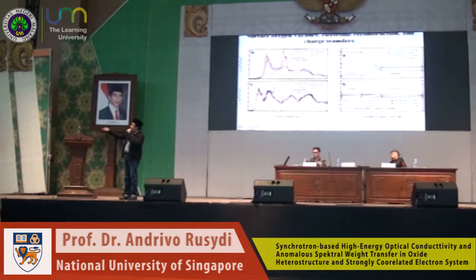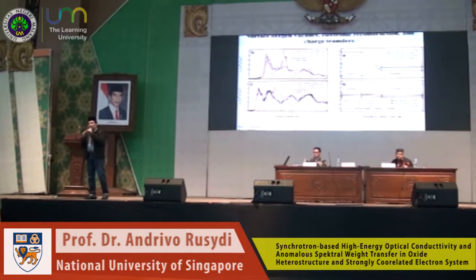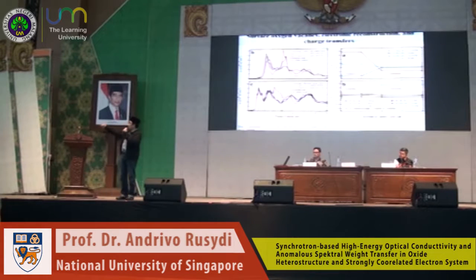This on the top part is the number of electrons of LAO with respect to bulk LAO. And the bottom part is the number of electrons in the interface of LAO-STO with respect to STO itself. So if you look at zero, that means there is no change in number of electrons. If you get a positive value there, that means there are additional electrons coming from somewhere. It has to come from somewhere.